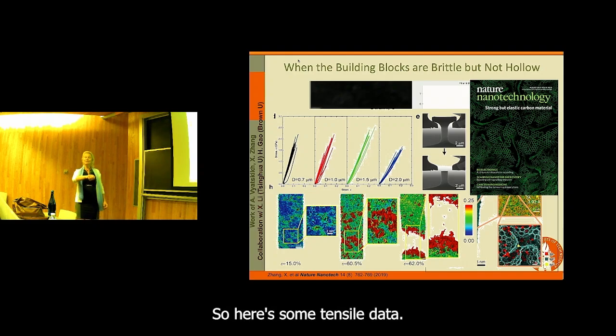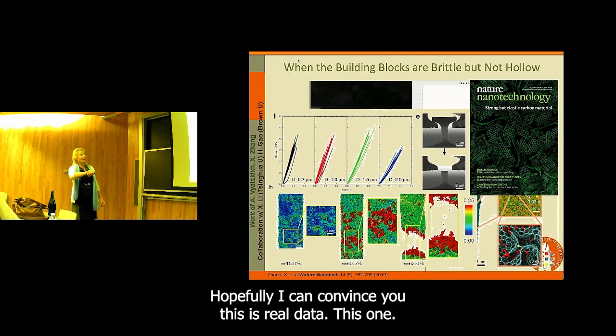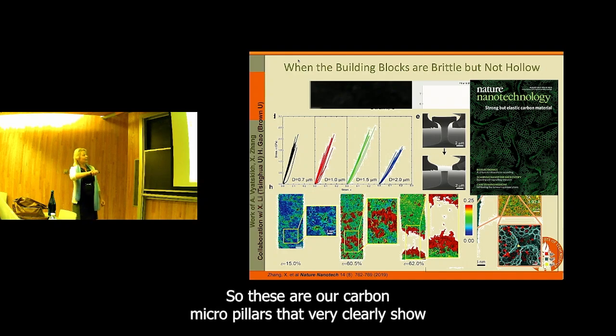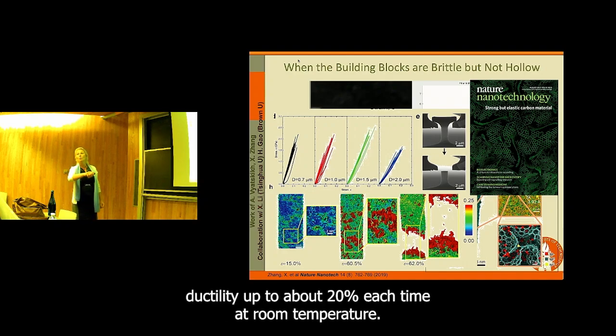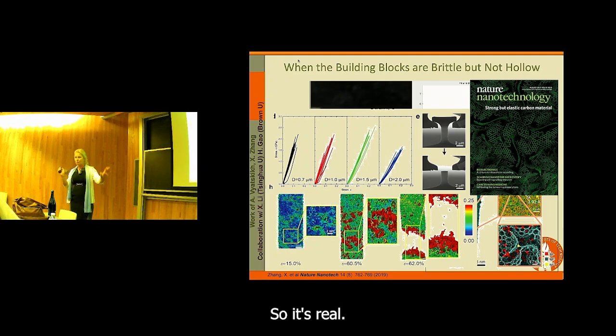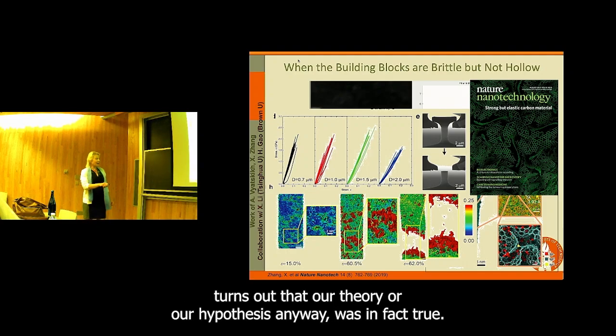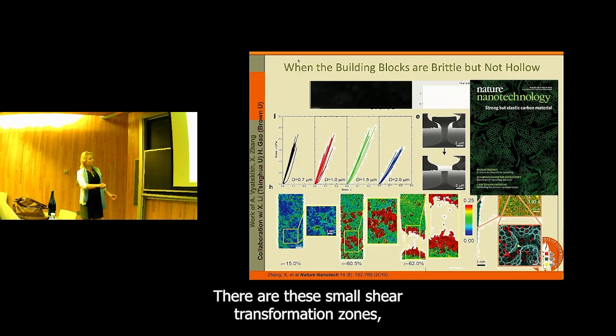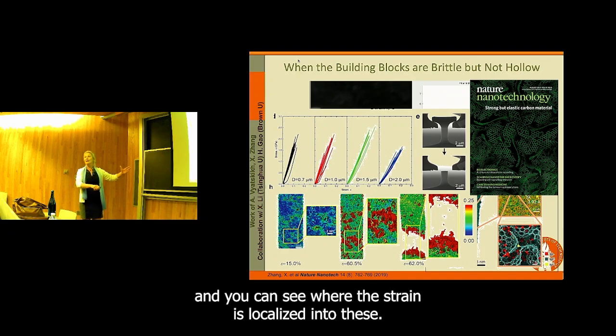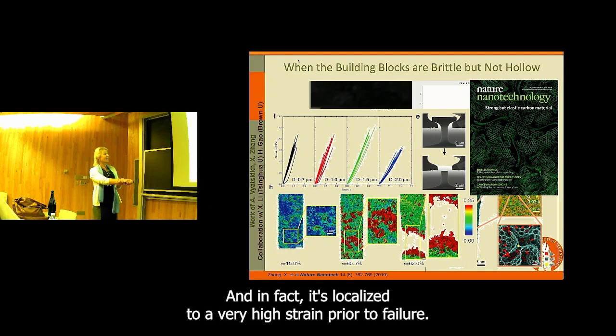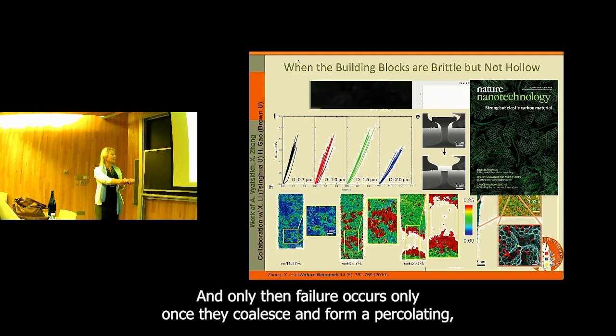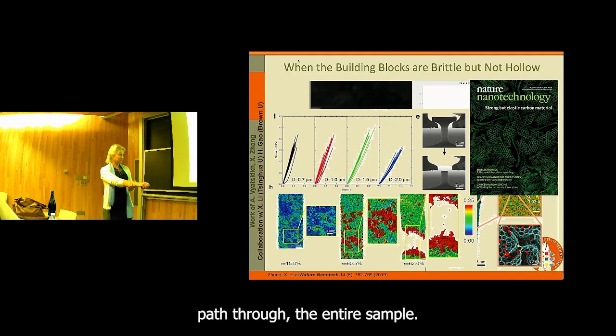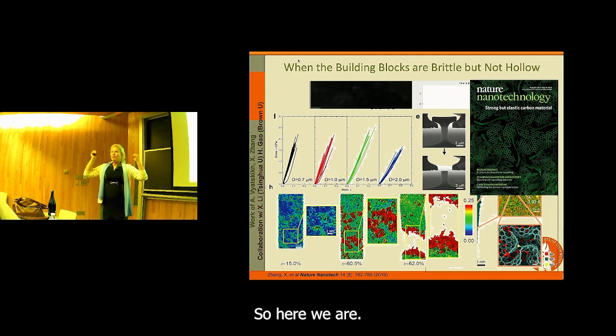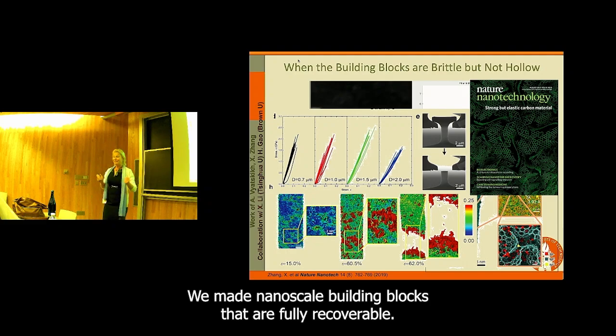So here's some tensile data. Hopefully I can convince you. This is real data. These are our carbon micropillars that very clearly show ductility up to about 20% each time at room temperature, so it's real. It turns out that our hypothesis was in fact true. There are these small shear transformation zones, and you can see where the strain is localized into these. It's localized to a very high strain prior to failure, and failure occurs only once they coalesce and form a percolating path through the entire sample. So here we are. We made nanoscale building blocks that are fully recoverable.